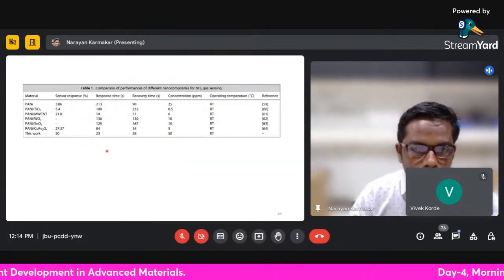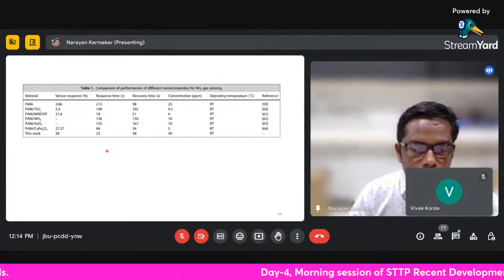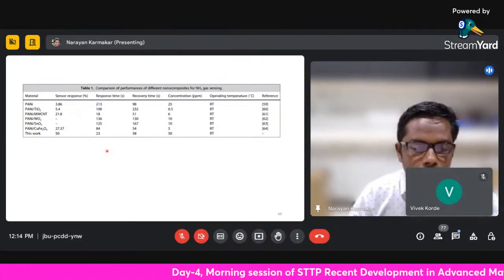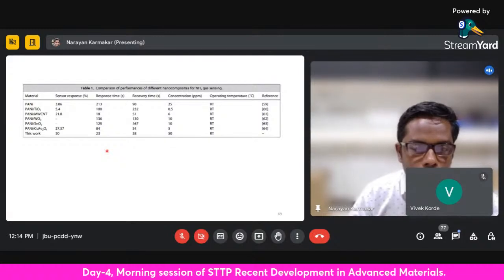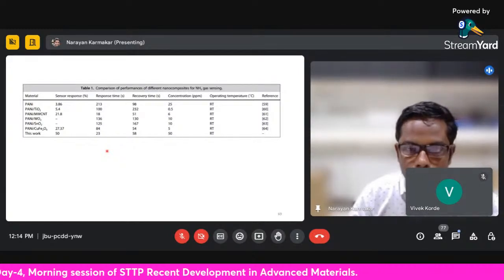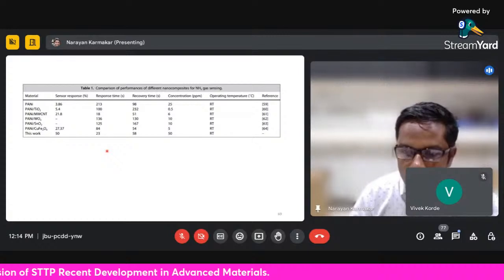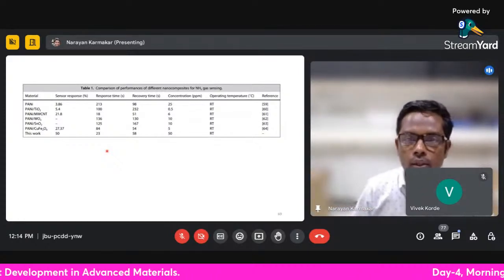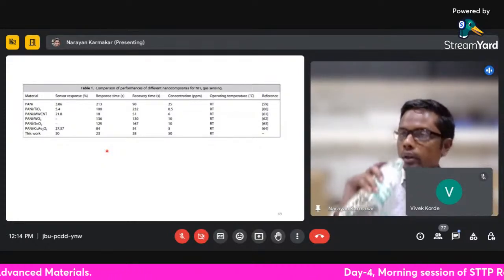This is mainly because of the chemical adsorption sites created by the silver nanoparticles, and because of the zinc oxide nanorods which are formed during the synthesis process. These are the procedures by which we synthesize these different nanoparticles.